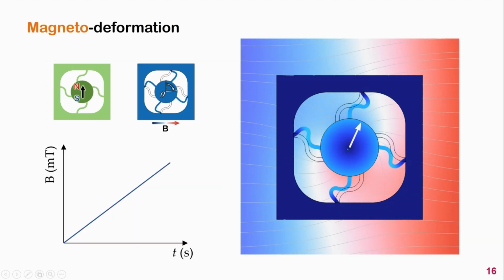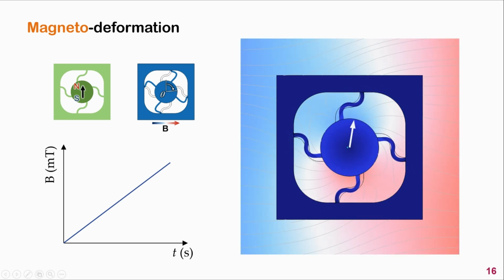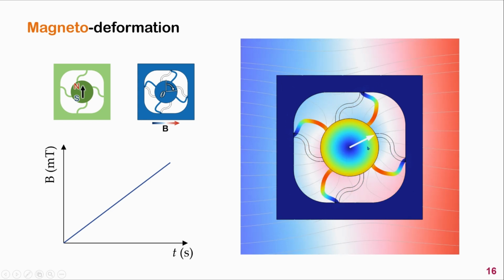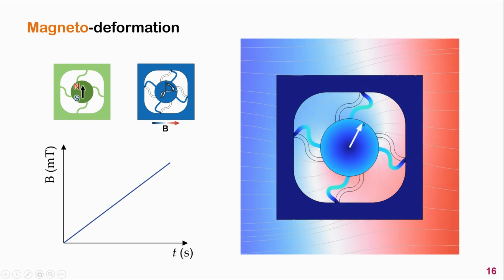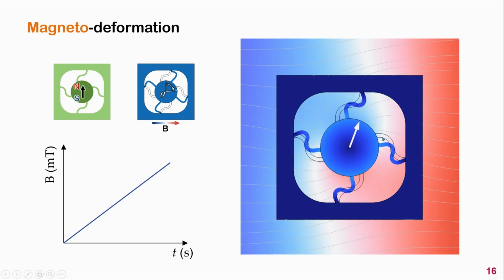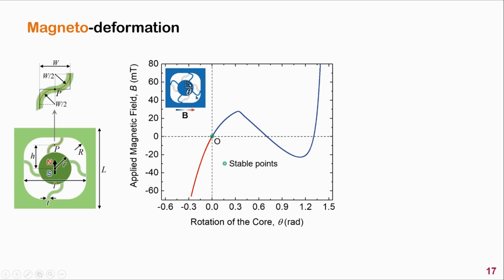As shown by this finite element simulation, as we increase the intensity of the applied magnetic field, the rotation angle of the mass core increases correspondingly. Then, at a critical point, snap-through behavior is observed. To quantitatively characterize the magnetomechanical behavior of the local resonance system, we calculate the